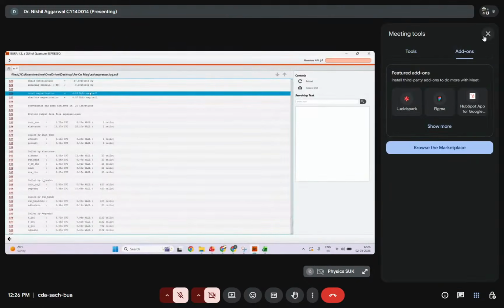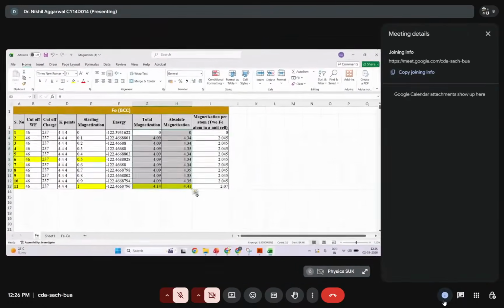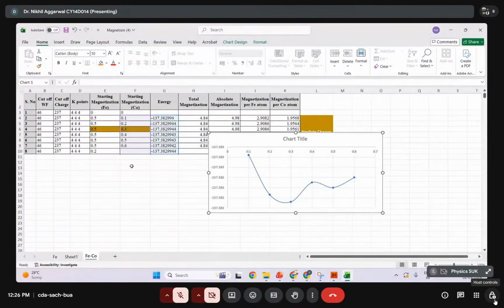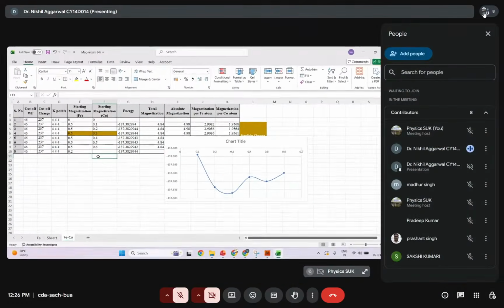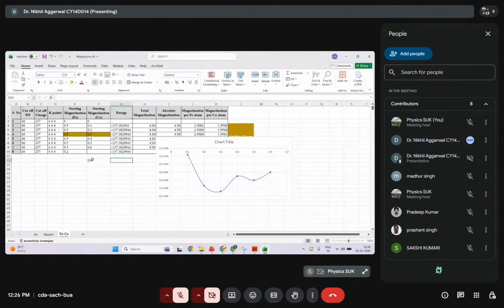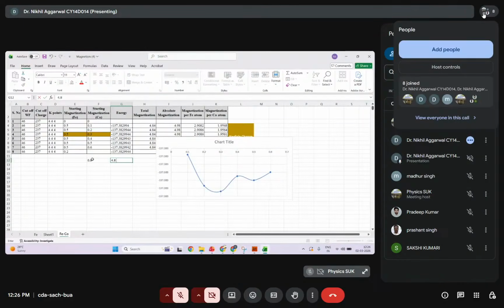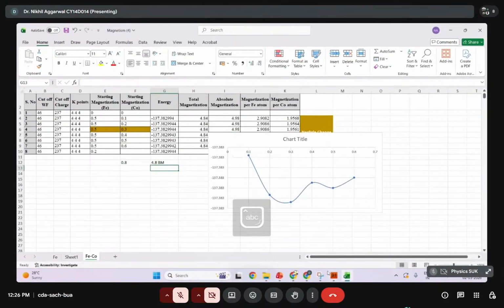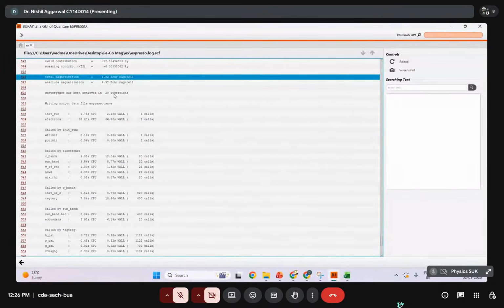I can see the value of the magnetization in Bohr magneton comes out to be 4.8 Bohr magneton per cell. This is for the iron cobalt lattice we have done, and we did it at 0.8. The value came out to 4.8 Bohr magneton. Now, there is additional information lying over here.